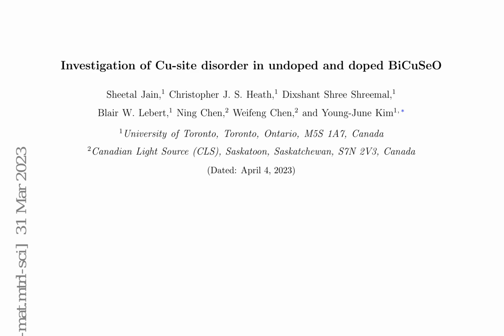In the compound BiCuSeO, known for its low lattice thermal conductivity, a study has been conducted to explore the thermal parameters of Cu and Ag. The findings reveal that these elements exhibit significantly higher thermal parameters compared to other elements in the compound, indicating a large thermal fluctuation which is temperature independent across most of the probed temperature range. This fluctuation is attributed to a rattling mode mechanism, where localized, independent vibrational modes at the Cu-site scatter phonons and